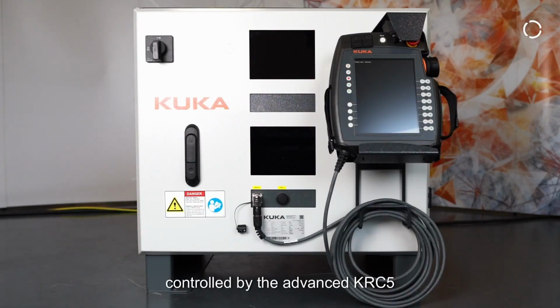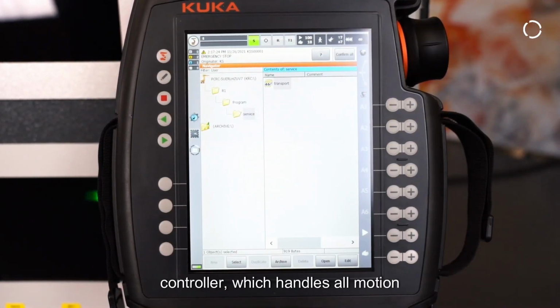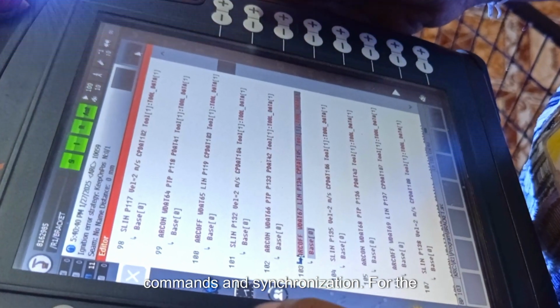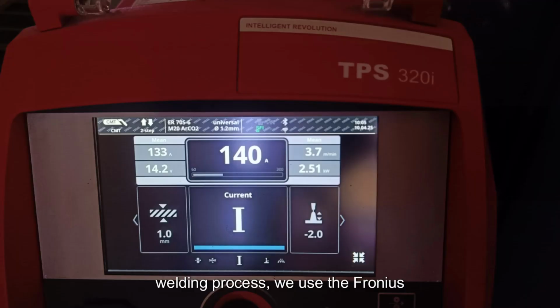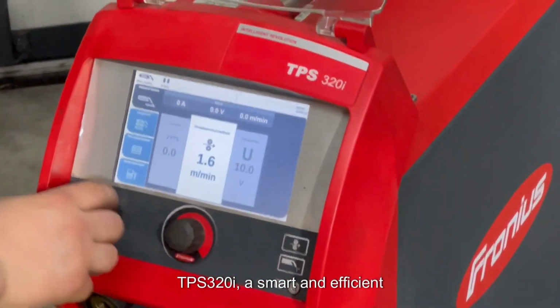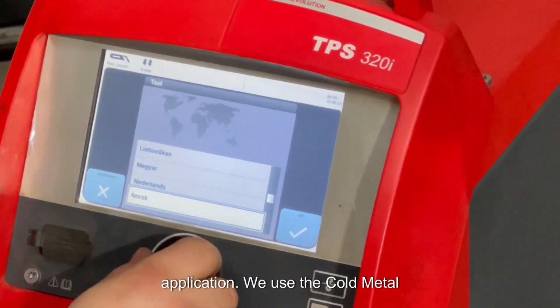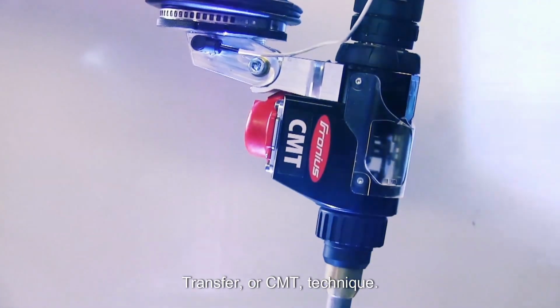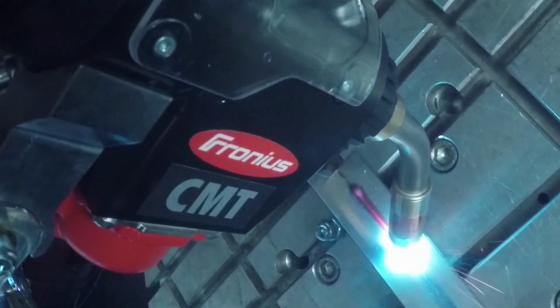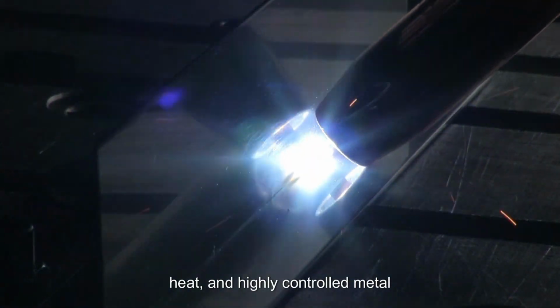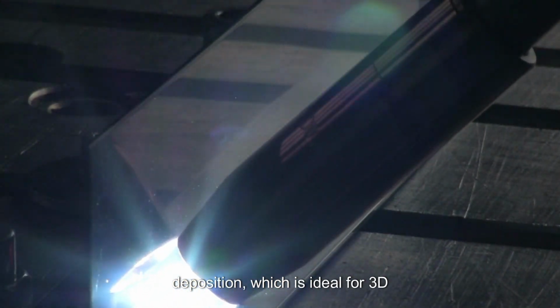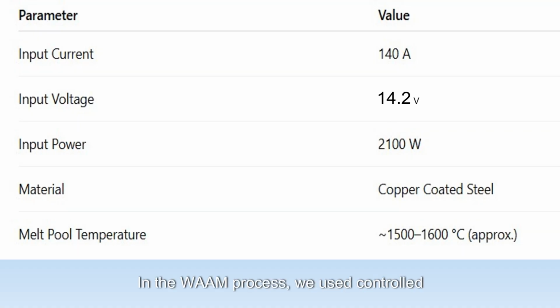This robot is controlled by the advanced KRC5 controller, which handles all motion commands and synchronization. For the welding process, we used the Fronius TPS320i, a smart and efficient welding power source, perfect for our application. We used the cold metal transfer, or CMT, technique. This method allows for low spatter, low heat, and highly controlled metal deposition, which is ideal for 3D printing metal parts. In the WAAM process, we used controlled welding parameters that are 140 amps current, 14.2 volts, and a 3.7 meters per minute wire feed, for smooth deposition and minimal spatter.